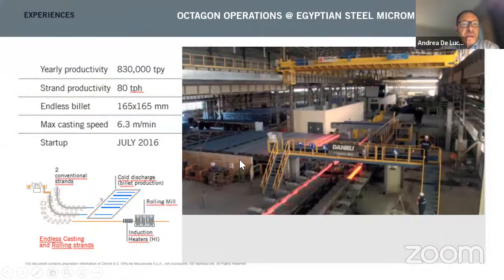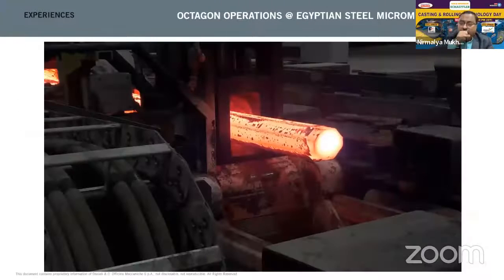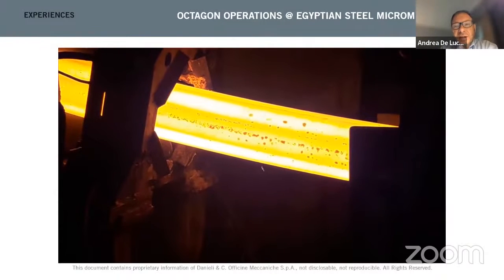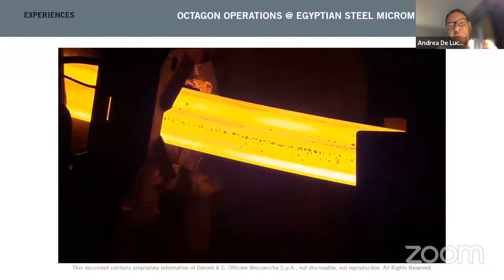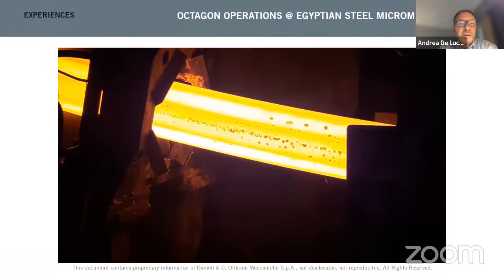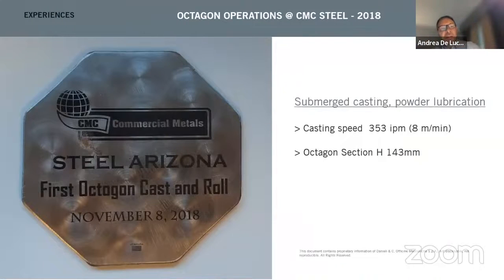Then we applied it two years later in Egypt. The size was bigger, equivalent to 165 by 165, and we reached 80 tons per hour with a single strand. You can see in this movie the homogeneous temperature in the octagon cast, which is one of the keys of the reliability and quality also in the rolling mill.